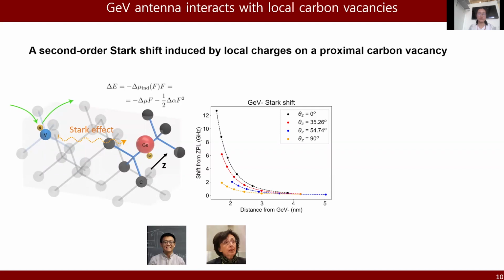In this specific work, the GeV is a very unique antenna system to experimentally study the antenna effect, because there are many naturally existing vacancies, like carbon vacancies inside diamond. We can study the near field from GeV by studying the interaction between the GeV and the carbon vacancies. We collaborate with Professor Jhuria, and we found that the carbon vacancy inside diamond can have a neutral charge state and a negatively charged state. The charge state switching of this carbon vacancy can induce a Stark shift to the GeV's ZPL. According to their DFT calculation, a vacancy that is 2 to 3 nanometers away from the GeV can induce a second order Stark shift of 2 gigahertz.